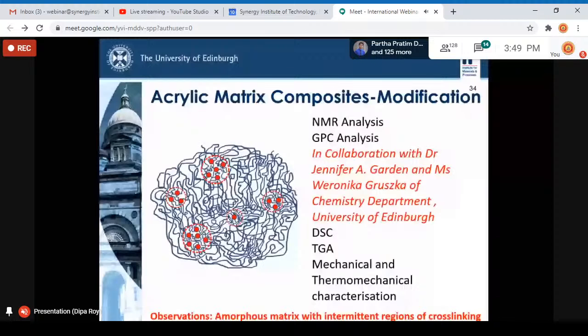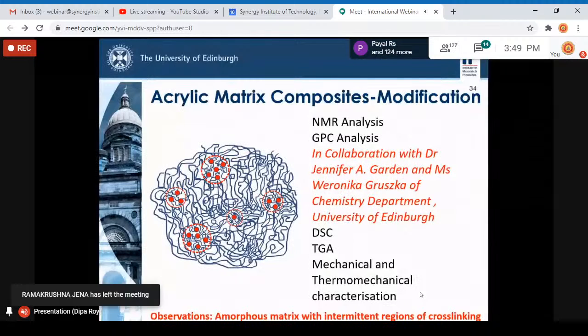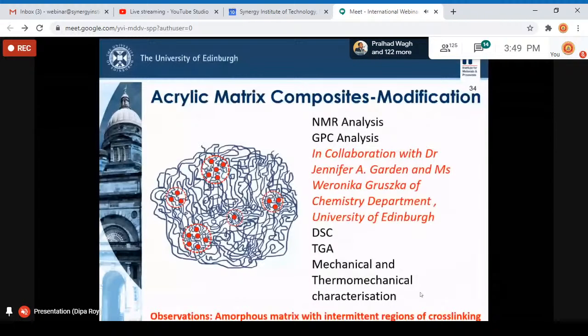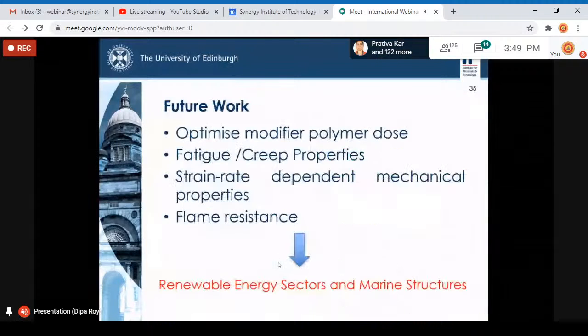We did a lot of different characterizations. I haven't included everything, but the thermal degradation behavior was enhanced. We saw some change in the exotherm in DSC. That was because of the reaction happening between the functional polyphenylene ether and the acrylic. There were quite a few different mechanical property changes as well. This was a very new observation for us because we could retain the thermoplasticity, but we could overcome some of the drawbacks of the acrylic matrix.